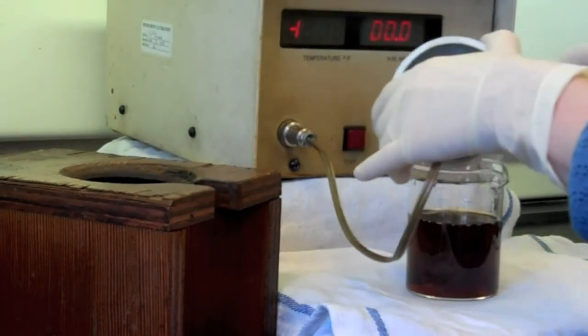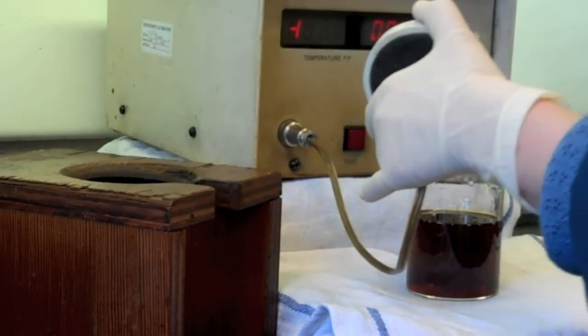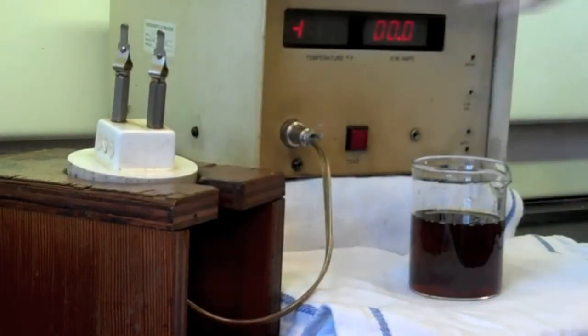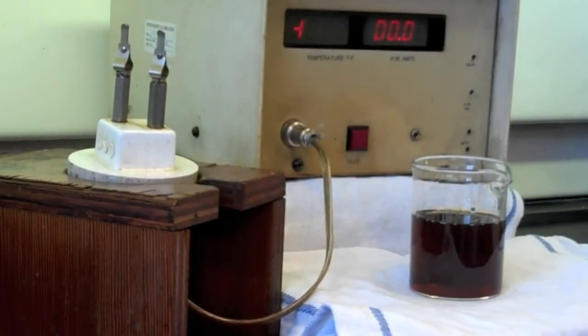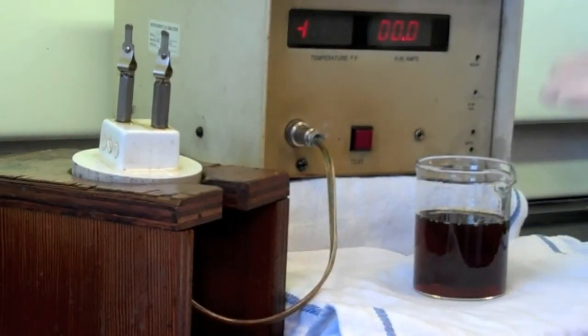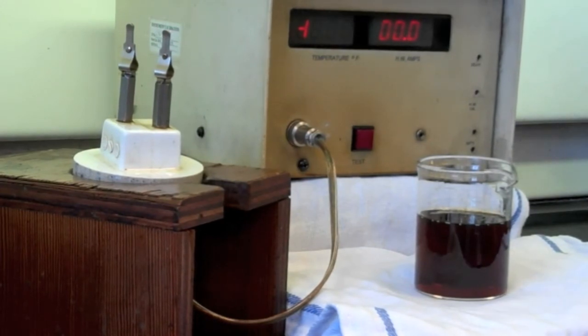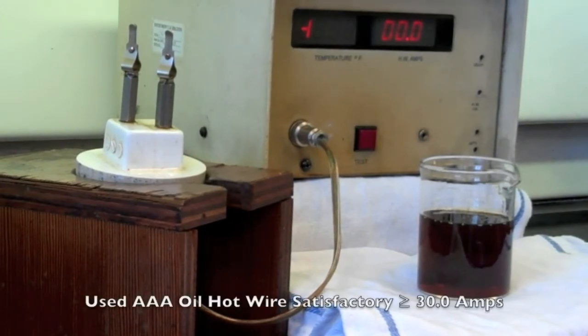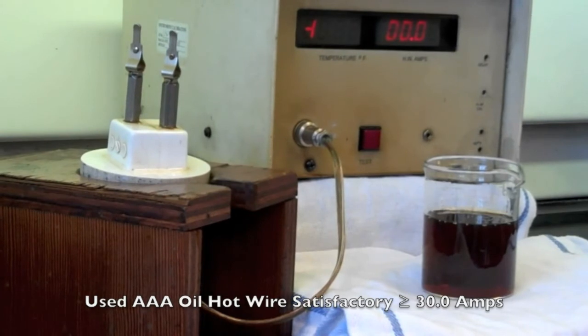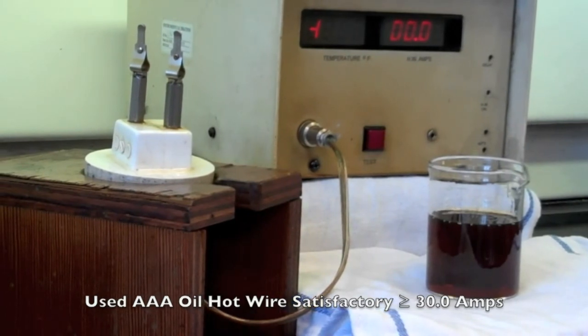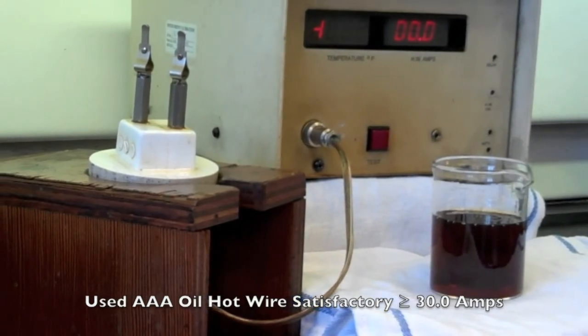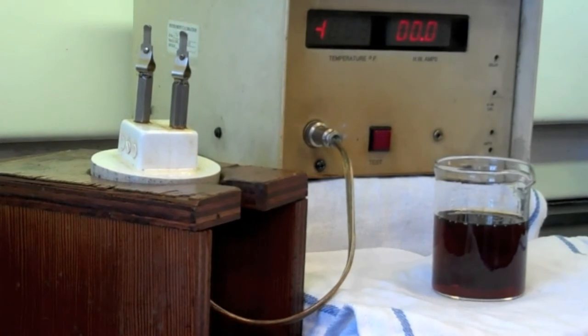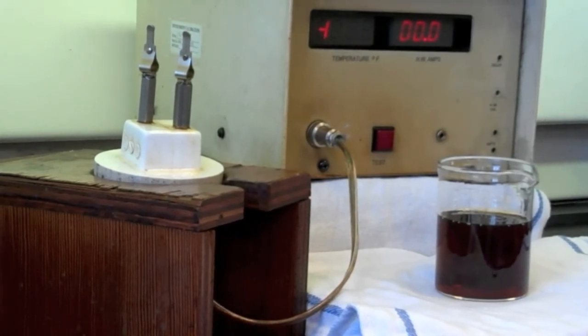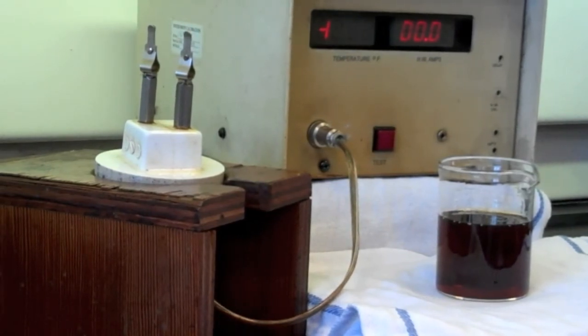We follow certain guidelines in reporting if the hot wire of an oil is satisfactory or not. In the case of a used AAA oil, the hot wire is considered satisfactory if it's at least 30 amps. If that's not the case, which is our oil too, then the quench speed of the oil is considered to